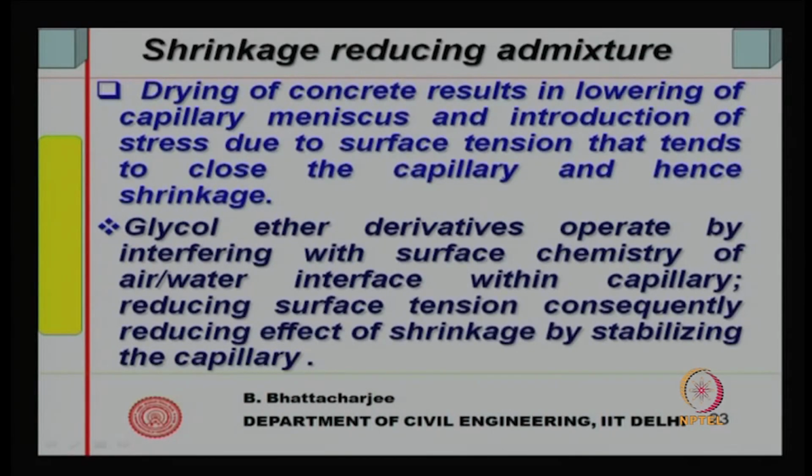Here also, once the surface becomes hydrophobic, liquid water cannot penetrate into it, you have to force it, but vapor can of course move. So, these are hydrophobic linings. There are varieties of other materials of this kind which do the job, but generically there are two types: one is hydrophobic pore lining and another is pore blocking treatment. All right.